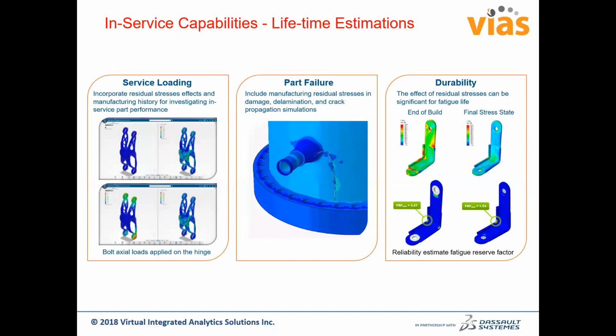In the middle one, you can see there is a nozzle which initiates a small crack, and then the crack grows under the given service loads. This example is not for an additive manufactured component; it is more of a vessel with a nozzle connection. But you can imagine you have an additive manufactured component. Simulation has given you all the residual stresses, all the distortions, all the material properties of interest, which is mostly yield and hardness in this regard. Now I can do a crack growth analysis on that, put the component under service load, and see how the crack is propagating under the given loading condition.